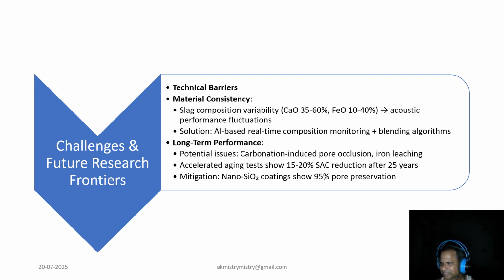Now coming to the challenges and future research frontiers. Yet challenges persist, like slag composition variability, especially in CaO and FeO, which can impact acoustic behavior very severely. AI driven blending and real time composition monitoring are tackling these issues. Long term performance threats like carbonation and iron leaching are being addressed through nano coatings that preserve up to 95% of pore structure after aging tests. We are overcoming technical hurdles with smart science.